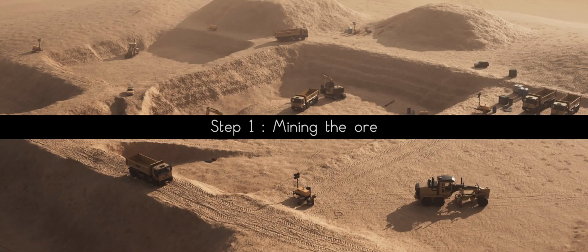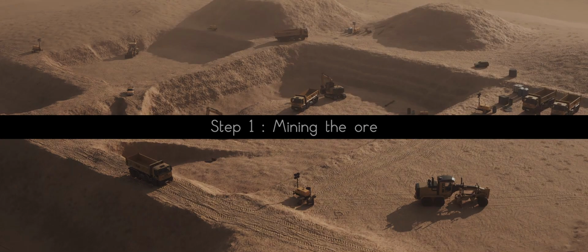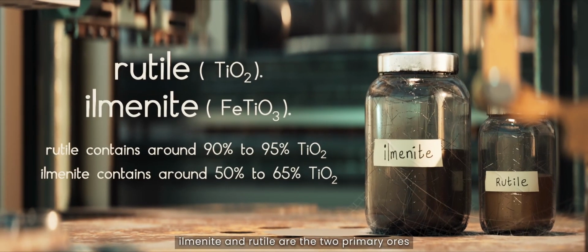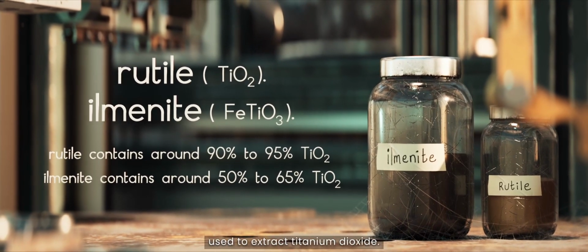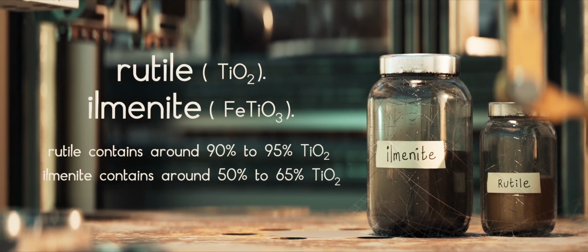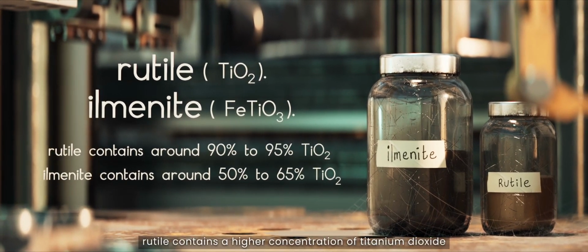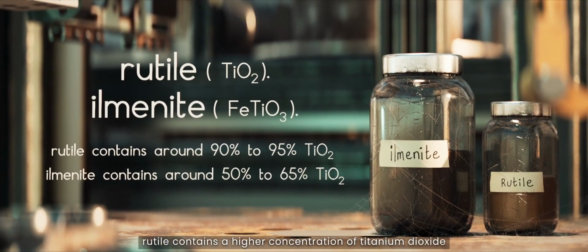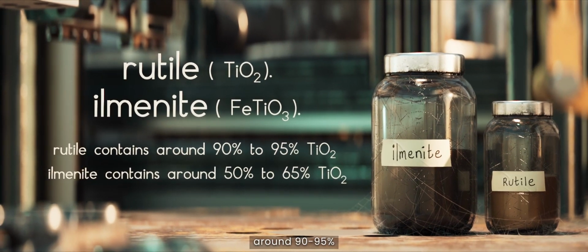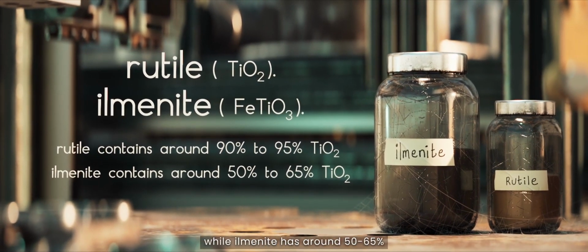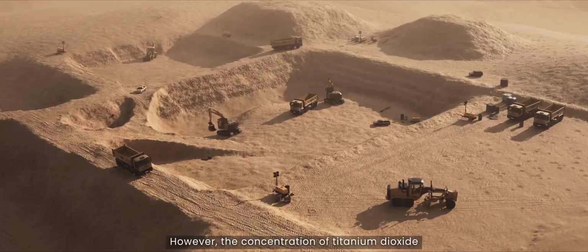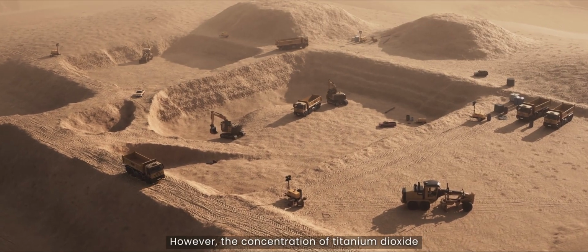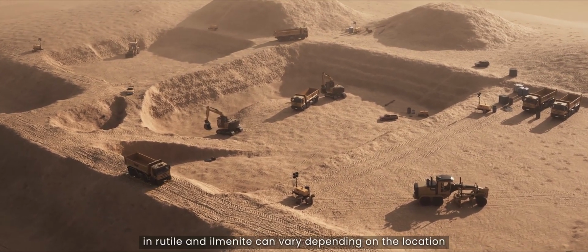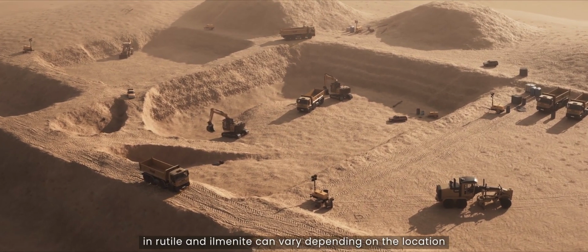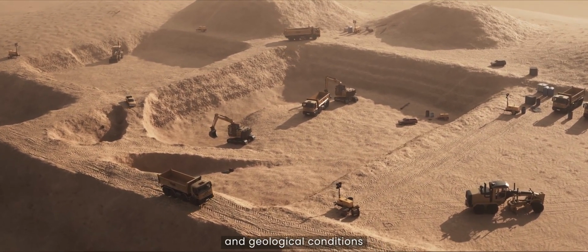Now, let's talk about Step 1. Mining the ore. Ilmenite and rutile are two primary ores used to extract titanium dioxide. Rutile contains a higher concentration of titanium dioxide, around 90 to 95%, while ilmenite has around 50 to 65%. However, the concentration of titanium dioxide in rutile and ilmenite can vary depending on the location and geological conditions.